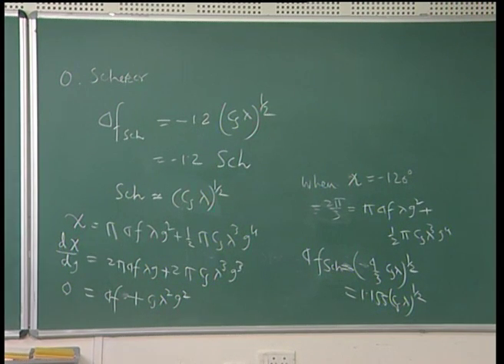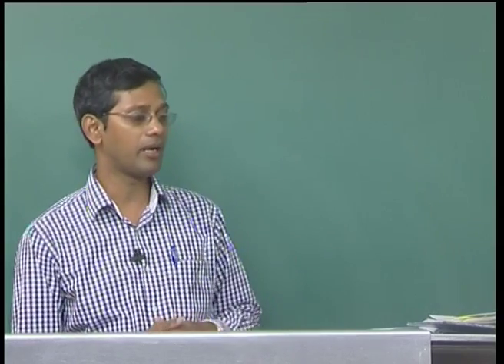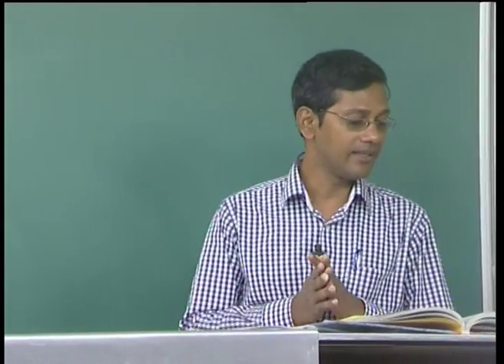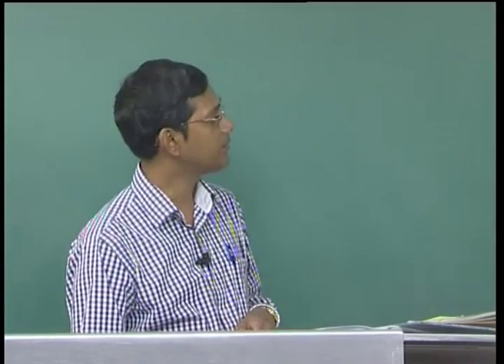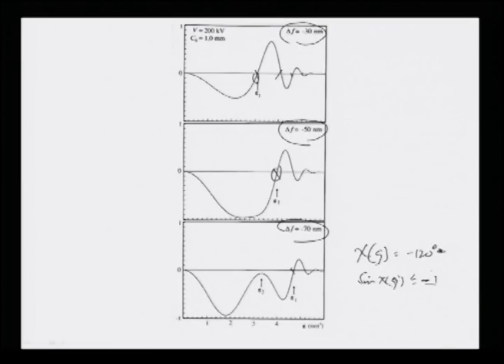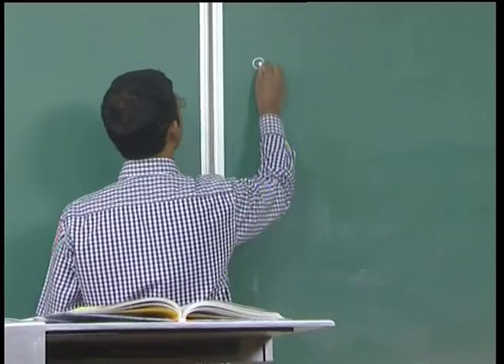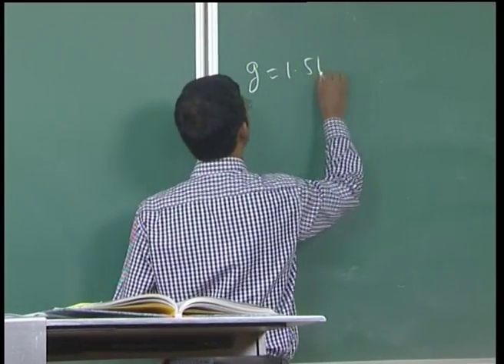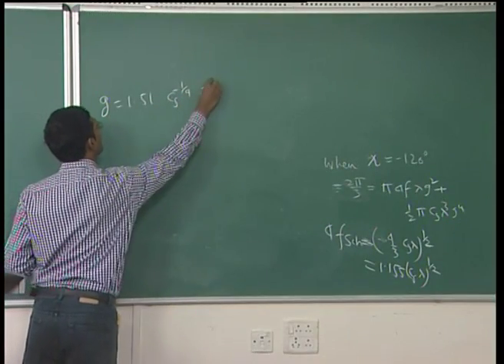And by fine tuning this calculation, one can arrive at the same Scherzer focus, which is nothing but that balancing act which you do of Cs by putting the focus value at a particular number. And this is routinely done in a microscope nowadays, where the optimum image is obtained at a particular value of Scherzer focus. Now, obviously, one can go to the next step, that is, the first crossover is given by this, and the next crossover can also be calculated. It comes at a particular g value, given by 1.51 Cs to the power minus 1 by 4 lambda to the power minus 3 by 4.